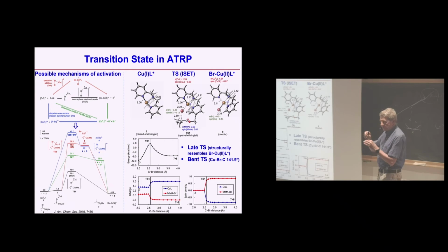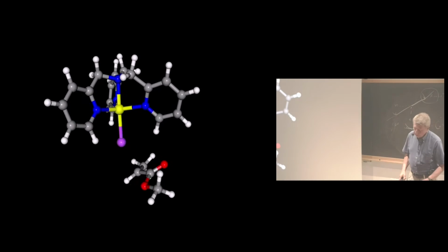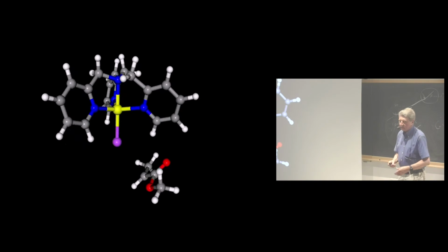Now, the transition state, which is the highest energy point on this trajectory, is very late. It means that it would resemble products rather than substrate. And it's also very unusual because you could see that this is not straight, it's bent. There is some electrostatic attraction between the negatively charged part of the acrylate and this positively charged copper species. So by looking at the transition state, it would have highly developed spin and charge, so it is really looking like a product nearly. So this is really how it happens: the alkyl halide will come a little bit from the side of this copper and then transfer this bromine through the transition state, which is one vibration essentially, and then can be reversibly activated and deactivated.